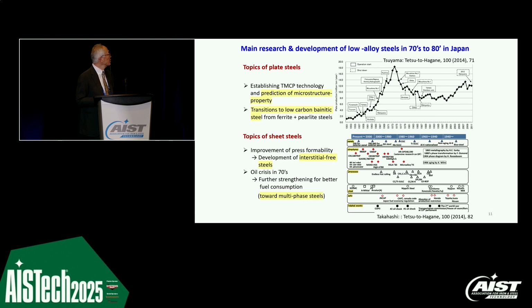So this is the main research and development of the low alloy steels in the 1970s and 80s in Japan. For thick plate, of course, TMCP is explored by replacing the microstructure from ferrite and pearlite to bainite. For the sheet steels, between the 60s and 80s, very soft iron was very important. So interstitial-free steel was developed for body design. And then after the oil crisis in the 70s, and also the importance of crashworthiness being focused on, we explored the higher strengths, toward multi-phase steels in the 90s and 2000.